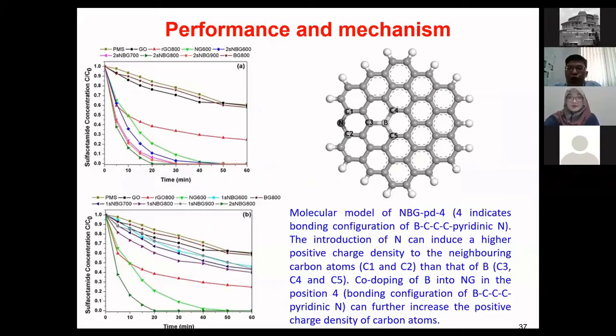So we also look into theoretical studies using density functional theory. Nowadays, a lot of people are looking into using DFT to model their catalyst, to design their catalyst so that they can use it for a particular application. So for this, we use it to study the mechanism and how this co-doping can improve the catalytic activity. And we found that if you have this boron attached in this configuration, you can see from the figure here. Nitrogen is over here, and boron is at this side. Okay, this one. So if you have this kind of configuration, you will get an increase in the positive charge density of the carbon atom, which means that somehow you can promote catalytic activity by controlling it like this.